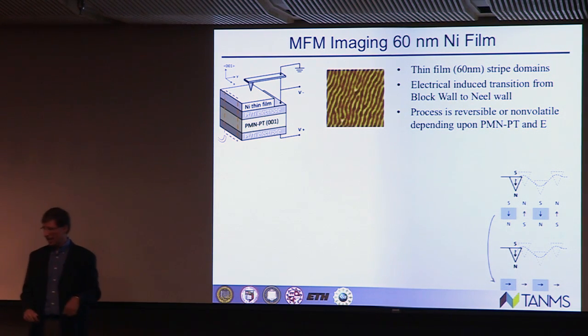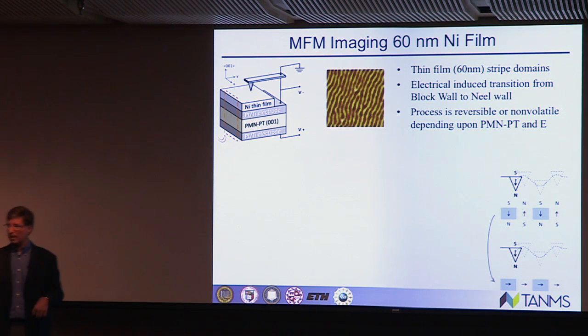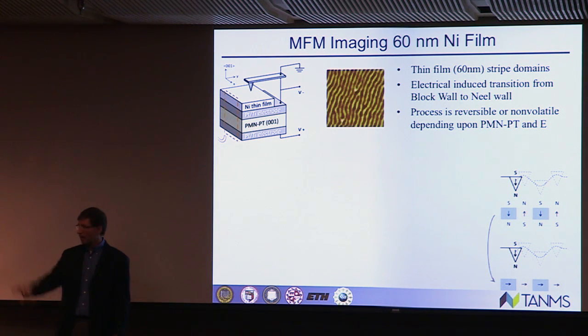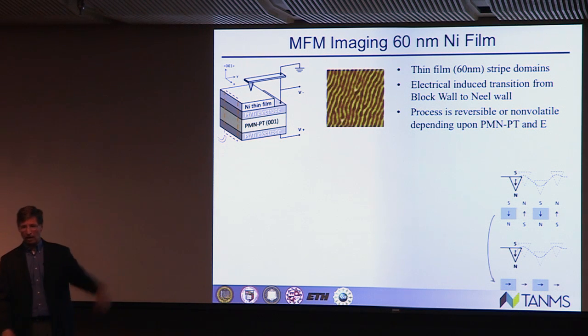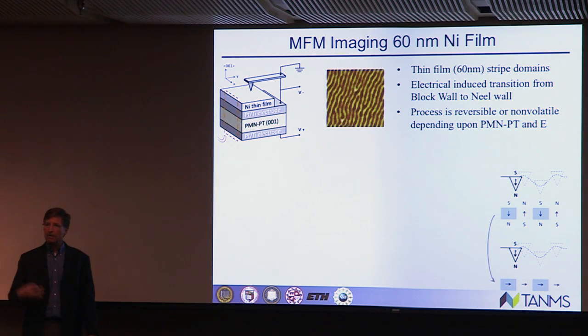Let's not look at magnetization curves. Let's look at MFM, magnetic force microscopy. What we're going to do is take this tip and just scan it along the surface. And what we argue is that you'll see local south and north poles coming out of this film. As this magnetic tip goes over it, it's going to create these stripe patterns. So you can imagine the black stripe is north, the white stripe is south. And the question is, can we control that?